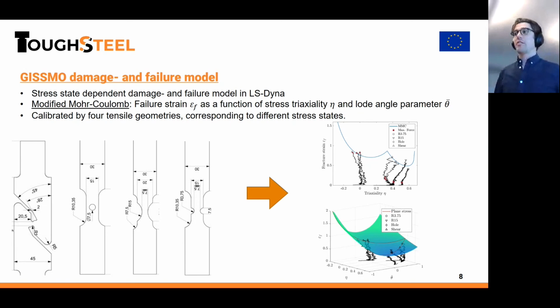The GISSMO models were calibrated to later be used in a shear cutting model, so we needed failure data for a wide range of stress states. We used tensile testing of different tensile specimens, which gave us a failure strain for a large range of stress states. The tensile testing data was used to calibrate a modified Mohr-Coulomb failure surface, which defines failure strain as a function of stress triaxiality and Lode angle parameter. This means that you can get failure data to be input in your GISSMO model that spans everything from plane strain compression, uniaxial compression, shear, uniaxial tension, and plane strain tension, to biaxial tension, and everything in between.